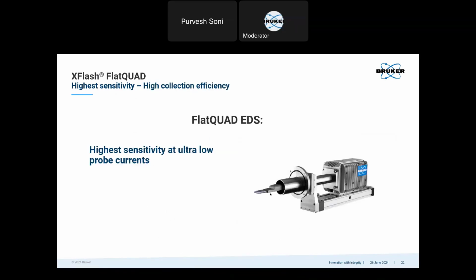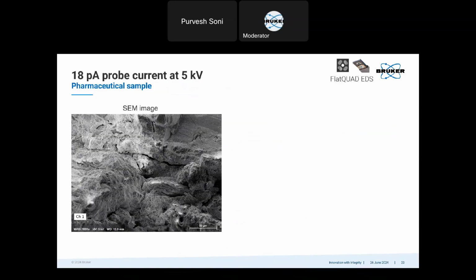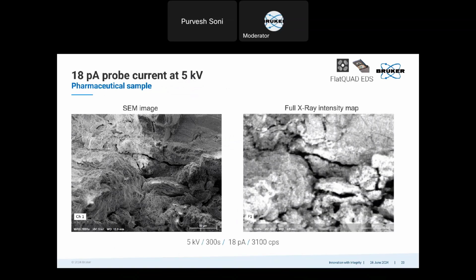So then let's see some ultra low probe current examples. This is a pharmaceutical tablet which was charging heavily, and because of this, I had to go to the lowest possible probe current on the microscope. It was 18 picoamperes at 5 kV. So this is what I got. So this is at 5 kV, 18 picoamperes.